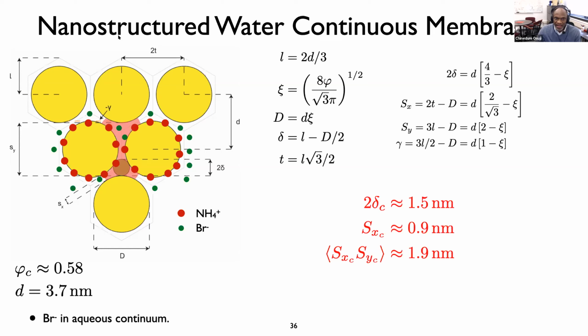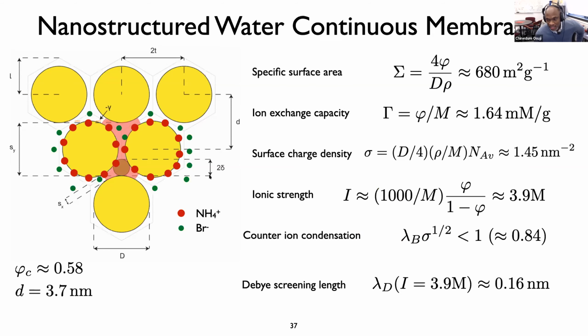And in this case, if we have transport perpendicular to the cylinders, then the transport regulating feature is defined by this dimension S sub x. If we have transport into the plane of the screen, then the transport regulating features are defined, for example, by this pink shaded area, and the largest circular cross-section that can pass unimpeded parallel to the cylinders is provided by this dimension 2 delta.